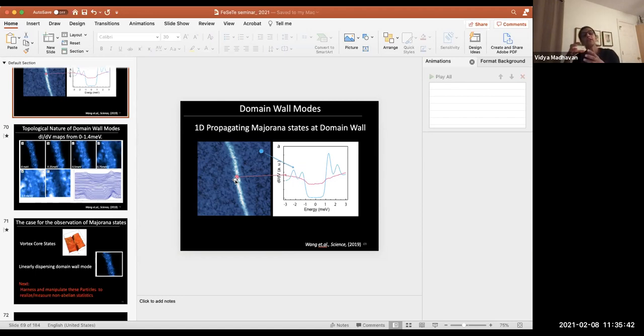You start with a topological insulator. It's not a superconductor, and then you proximitize it with a superconductor, and remember the bulk is s-wave. The surface state, the proximity effect is also s-wave. What I mean by that is the surface state is fully gapped. So there's no p-wave here at all. But you can show that under certain circumstances, it effectively behaves like a p-wave. And the circumstances are very special.